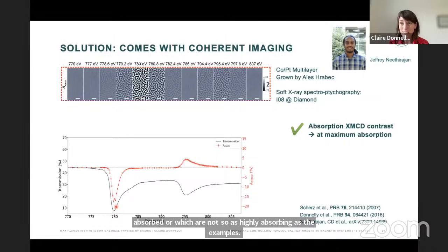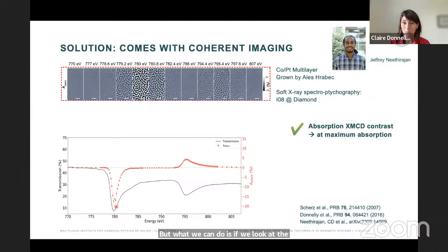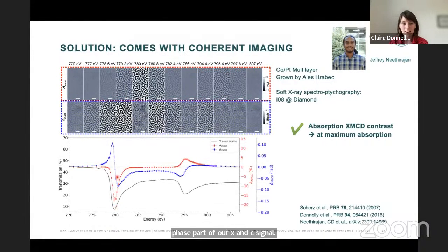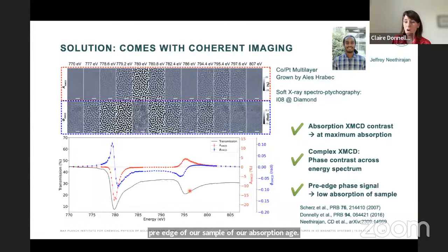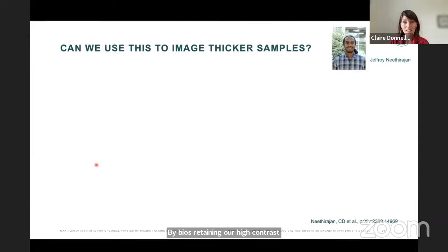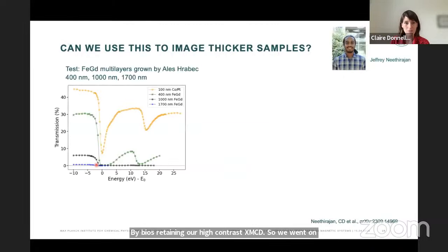But if we look at the phase part of our XMCD signal, we see that this blue signal, which is the phase, is no longer limited to the regions of high absorption, but extends into the pre-edge of our absorption edge. Because it extends into the pre-edge, we can image this same sample at an X-ray energy where we have much lower absorption, and that offers the potential to go to thicker systems while retaining our high contrast XMCD.